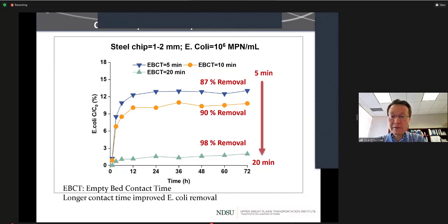And based on our results, we observed that when the EBCT or contact time is 5 minutes, we were able to maintain 87% removal over 72 hours. And when we increase the contact time to 10 minutes, we were able to achieve roughly 90% removal. And when we further increase the contact time to 20 minutes, then we were able to achieve 98% removal. Overall, for a wide range of contact times, 5 to 20 minutes, we were able to achieve very good removal efficiencies. So that means this filter technology can be adopted to different stormwater events that have different flow volumes, which will result in different filter contact times.